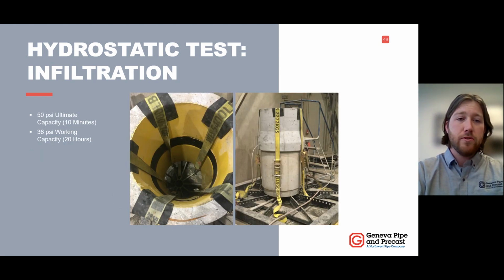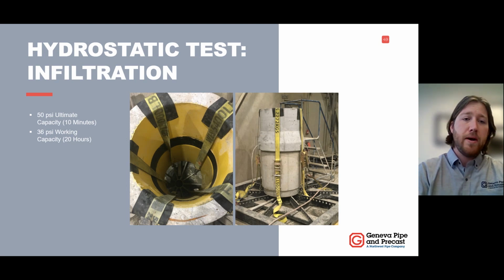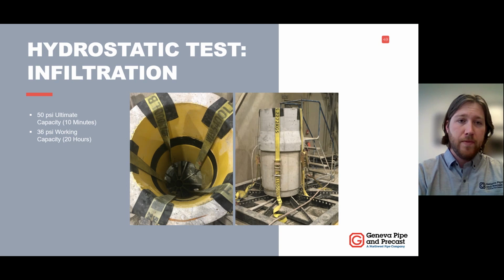Secondly, we wanted to test for infiltration. Another cost associated with failing infrastructure is the increase of water that needs to be treated. So this one, it's kind of hard to see, but there in the right photo, we drilled a hole through the bell of one pipe joint, and we introduced a positive pressure behind the coupler to test those gaskets to see what they could hold. These held at over 30 PSI for 20 hours, which again is a lot of head, more than you will see in most typical installations.